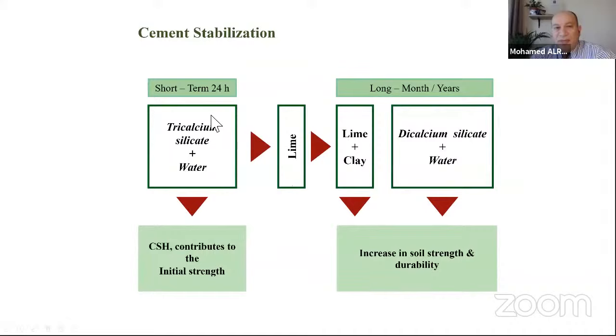For the cement stabilization, the major element affecting the strength comes from this reaction: when we hydrate the tricalcium silicate by adding water, we get calcium silicate hydrate particles. And again, in the long term, there is another component inside the cement itself, the dicalcium silicate.